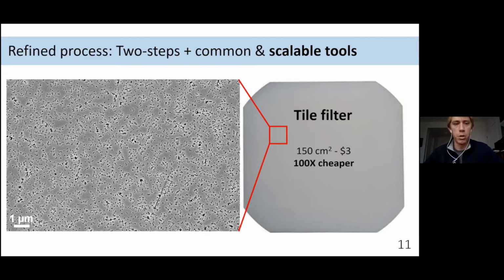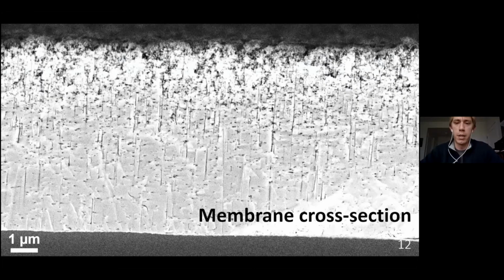So looking in the cross section, if we were to cut this wafer in half and look at the cross section in SEM to give you a bit better an idea of the morphology, we can see at the very top of the slide here the initial chemical etching surface where we initially deposit that catalyst. And then these long dark contrast lines are representing the nanopores or channels themselves, which run from top to bottom of the membrane. That really allows the solvent, be it water or some other organic material, to be forced through the membrane under pressure, while the diameter and chemical character of those pores is actually dictating what can and can't pass through the membrane.